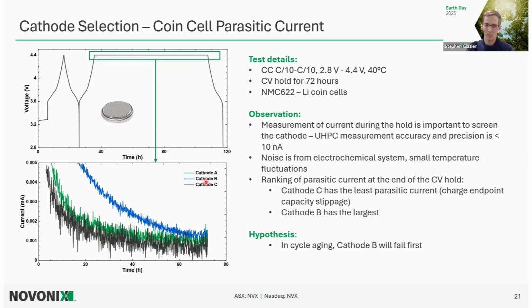We can say, okay, cathode B has a much higher parasitic current occurring, and so likely has the most of these slippage-based mechanisms. And this is raw data right from the cycler. This isn't smoothed or averaged. And our UHPC is accurate and precise to less than 10 nanoamps at this level. So any of this noise that we're seeing here is actually real data. It's not just noise in the cycler system.